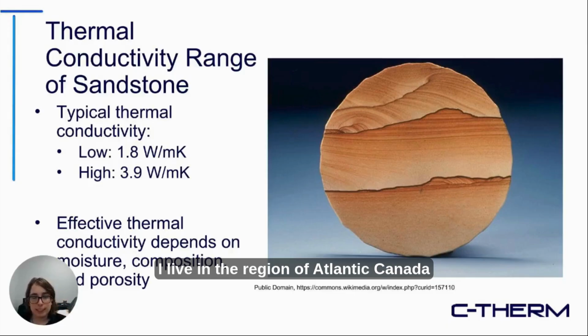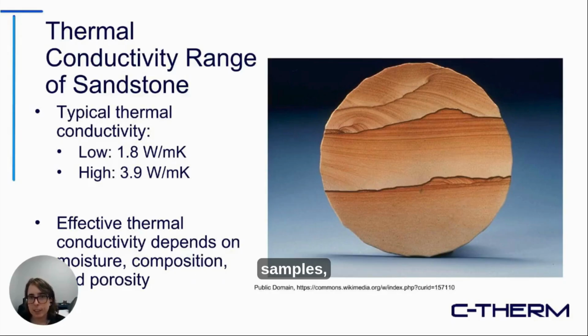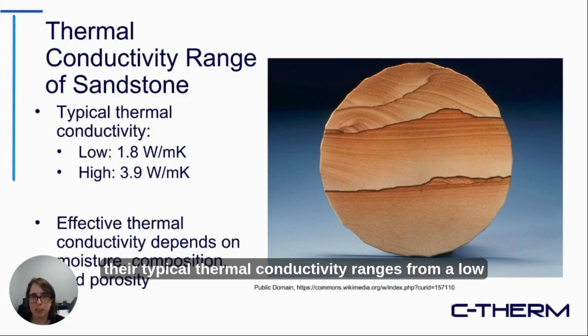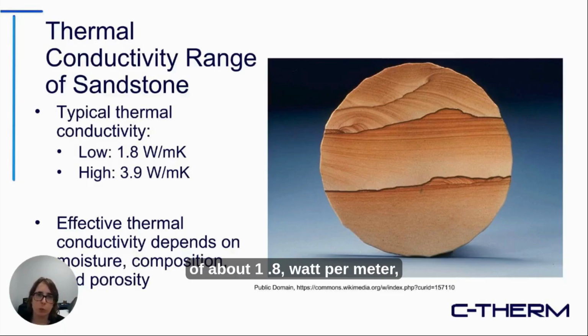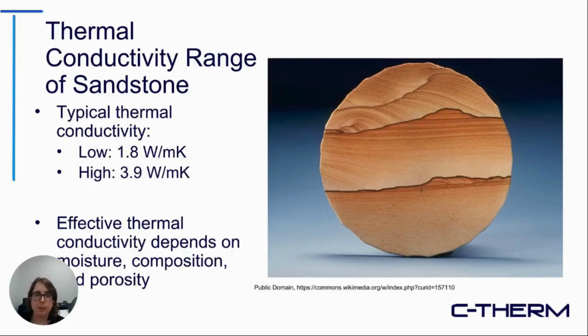I live in the region of Atlantic Canada, and along the coast here, you'll see cliffs that are sandstone based in many areas. These kinds of samples' typical thermal conductivity ranges from a low of about 1.8 watt per meter Kelvin to a high of about 4 watt per meter Kelvin, give or take.